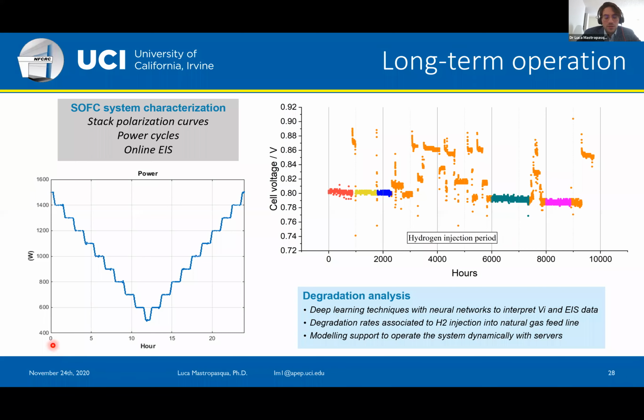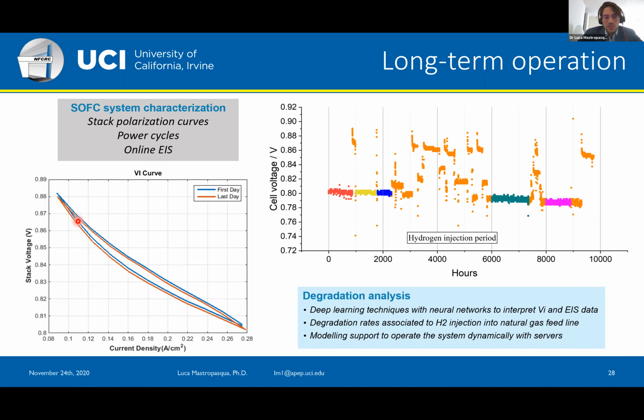In this case, I just want you to notice the time that we need to allow for performing a polarization curve. This is basically a 1-day cycle, because in order to reach thermal stability or a steady state in the two stacks, the thermal inertia of these stacks is quite big, so we need to allow sufficient time to reach the thermal steady state of the system. And even here, we still see a hysteresis between the forward and backward branch of the polarization curve because of this thermal inertia of the stacks.